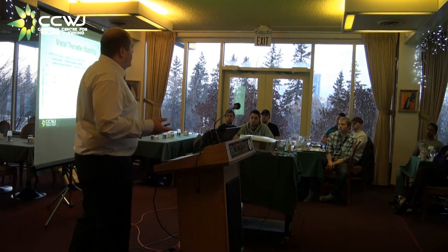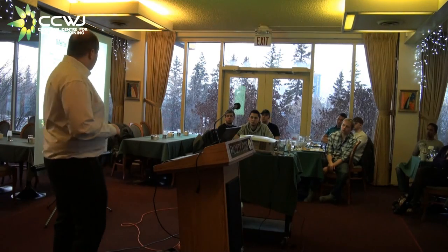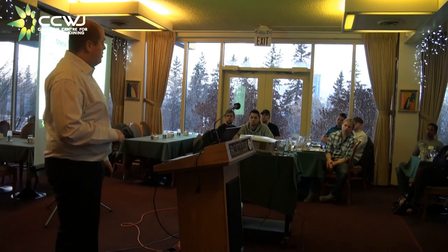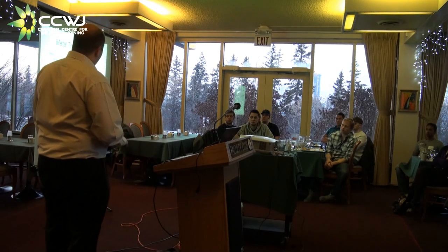Now, people might say that, well, it's not very productive. Well, these wires, since they are tungsten carbide, are actually fairly heavy. So at this slow wire feed speed, 120 inch per minute, which is really slow, we are still depositing 7 pounds an hour with a 16th inch wire. So it's still relatively productive already at the optimum parameters. Now, if we use a bigger wire, say 2 millimeter or 2.4 millimeter, and we can find these optimum regions, our productivity goes up naturally.